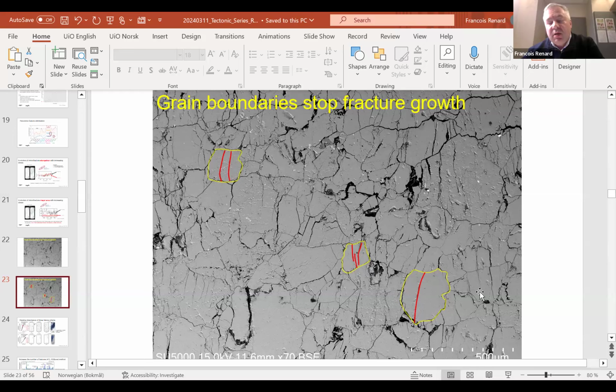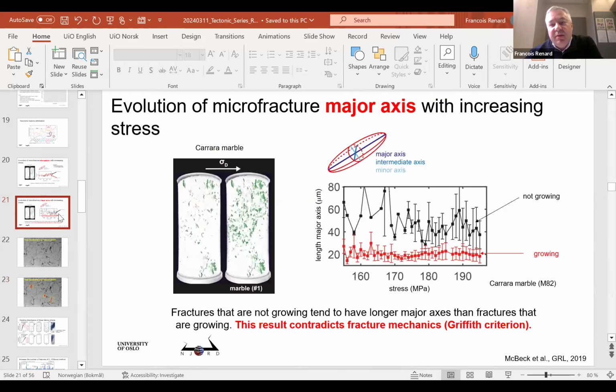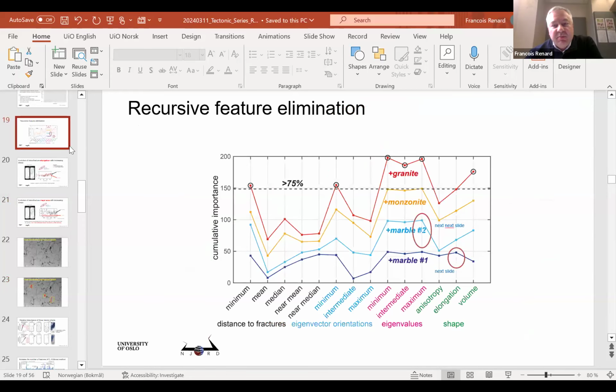So that's the reason. And probably it comes also from the strong anisotropy of calcite, because those are calcite grains, and calcite has cleavage planes that are very weak. So once the cleavage breaks, it breaks, but breaking perpendicular to the cleavage, the fracture energy is much larger. So it is completely due to the boundaries between grains then? Yeah. So you have seen this only on Carrara marble or also on other rocks? Yeah, because on other rocks, I would have the same thing.